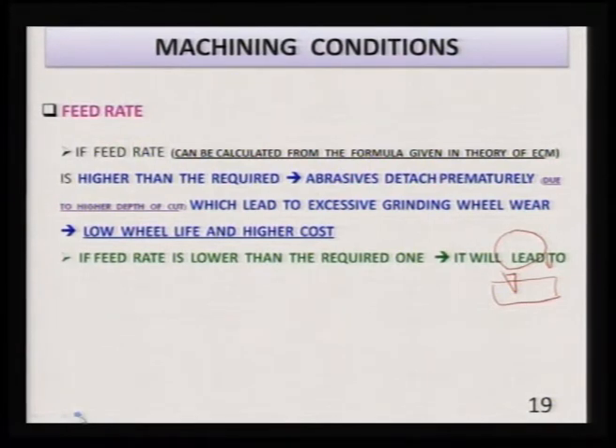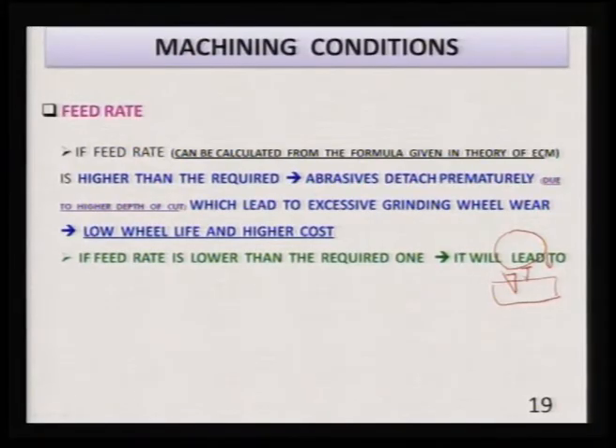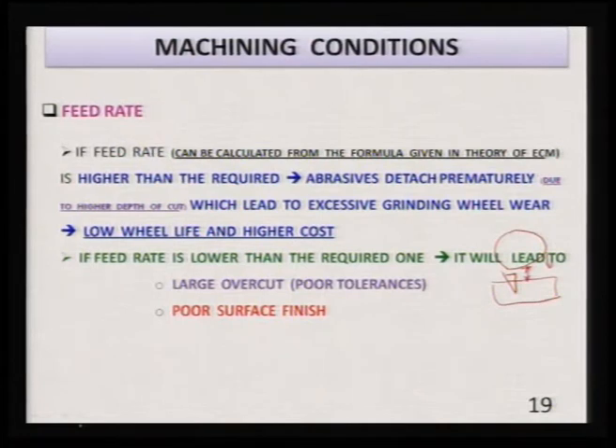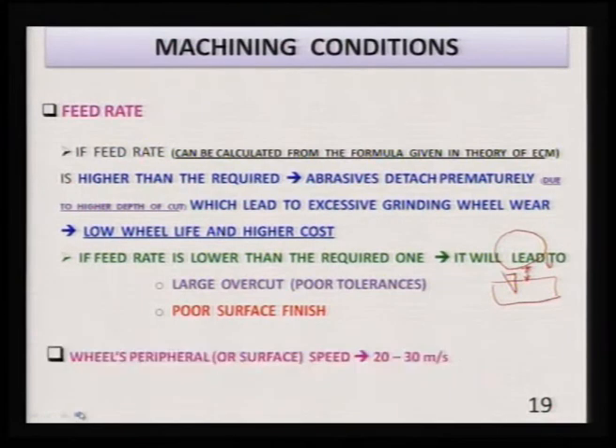If feed rate is lower than the required one, then what will happen? The inter-electrode gap will increase. That means, this gap will increase, and if this gap is more than really the required one, then you will get larger overcut, that is the poor tolerances, and you will also get poor surface finish, and both are undesirable features. And wheel's peripheral speed normally is 20 to 30 meter per second in case of electrochemical grinding.